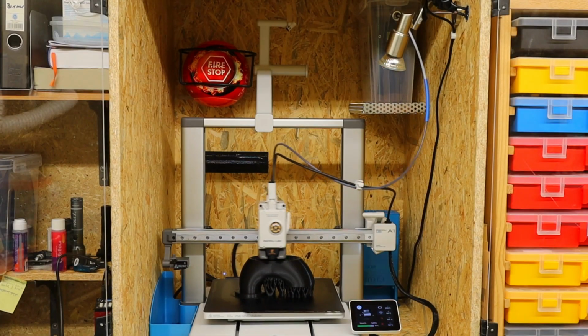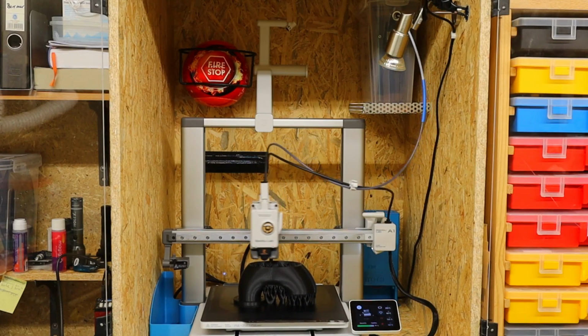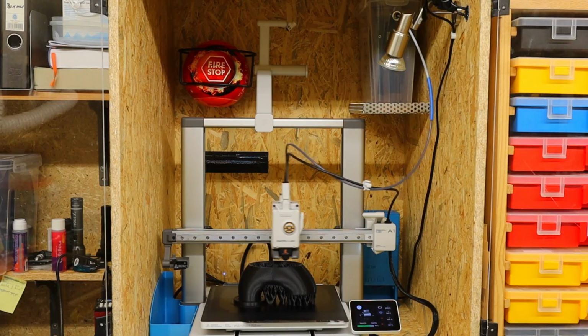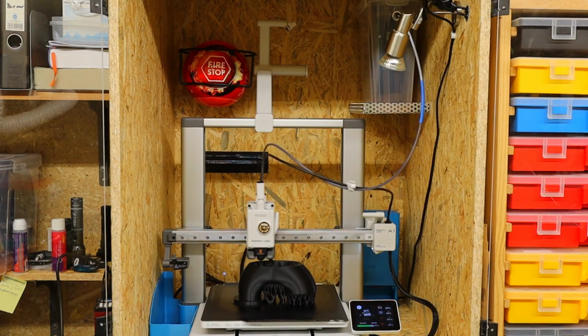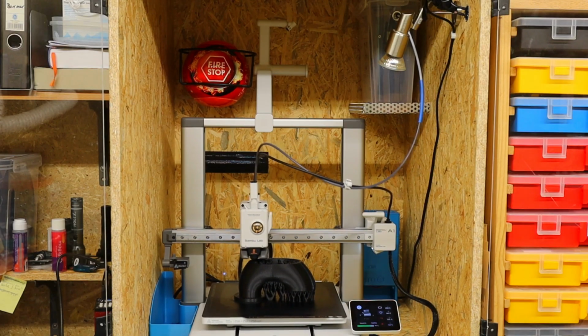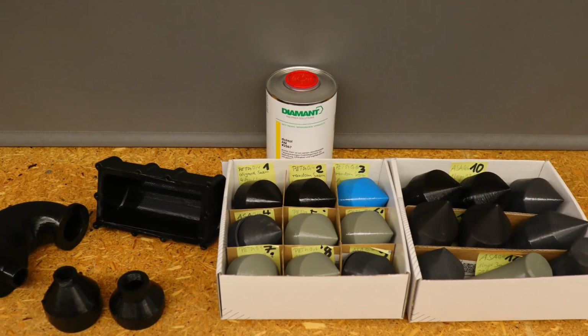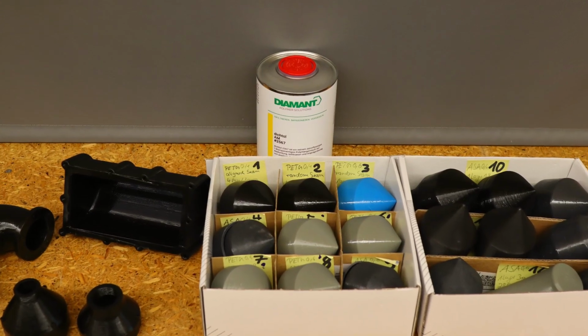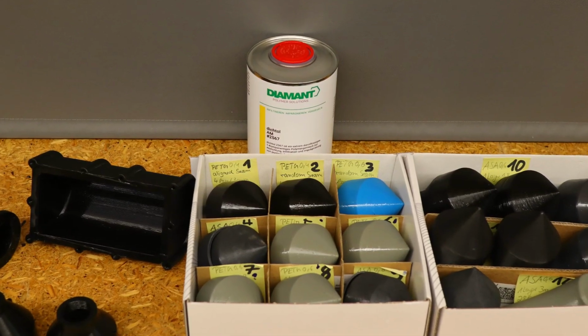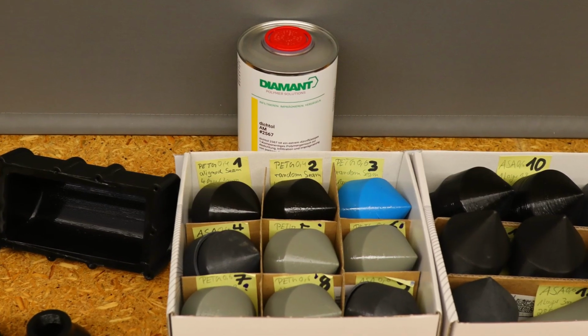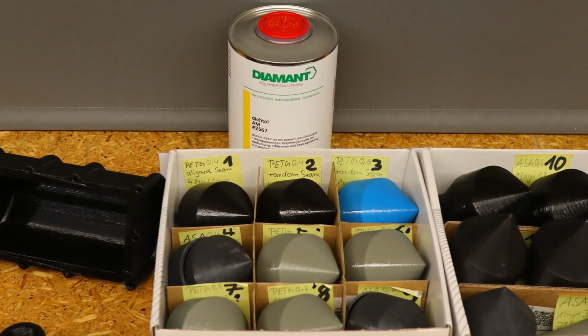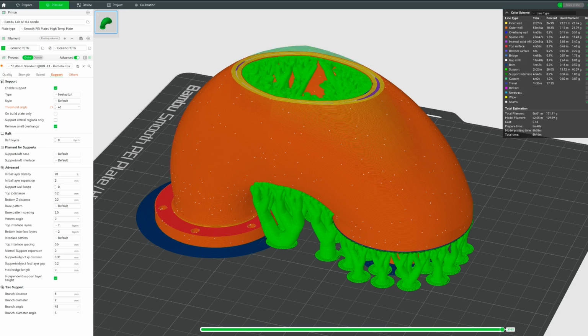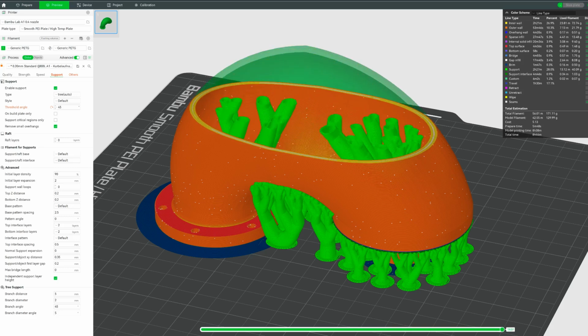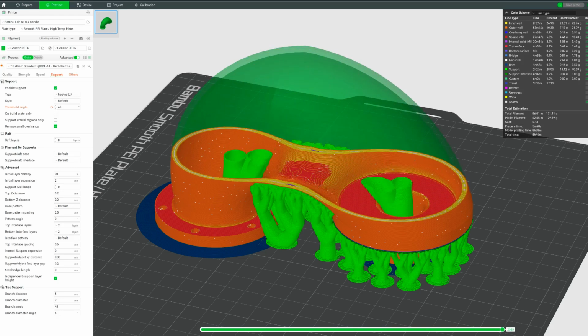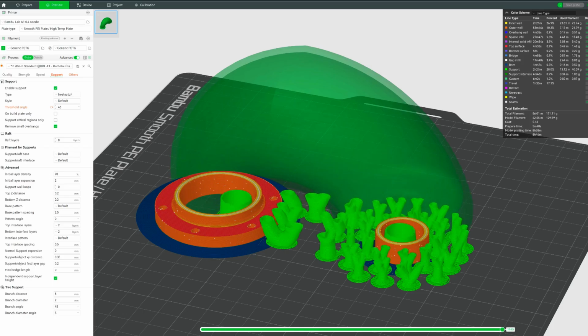PETG has continued to prove itself as my favorite filament. Not only has it withstood the highest pressures without ever exploding, it always leaked in a controlled manner. The Dichtol fulfilled my expectations. Although the test pieces were not optimal for the treatment, the strength of the printed layers determined the compressive strength and not the sealant. The printing settings of the seams and similar in the slicer are no longer so important. Minor printing errors are reliably sealed by the Dichtol.